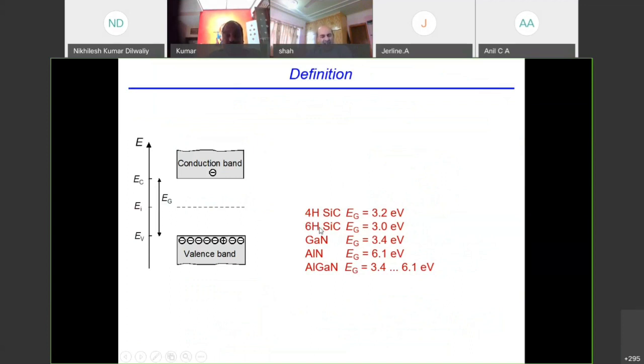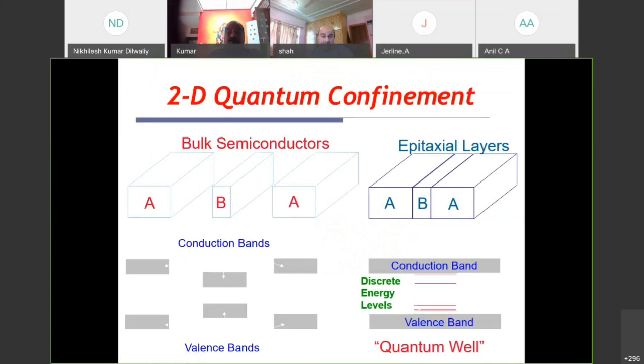You can see here in the hexagonal form, the band gap is 3 eV, whereas in the 4H SiC, it is 3.2 eV. So if the binding energies with respect to one atom of silicon and carbon vary, accordingly the band gap can vary. Whereas for gallium nitride, you see 3.4, and aluminum nitride, you see 6.1. If you mix aluminum nitride and gallium nitride, you can have a band gap from 3.4 to 6.1. So this is the 2D confinement.